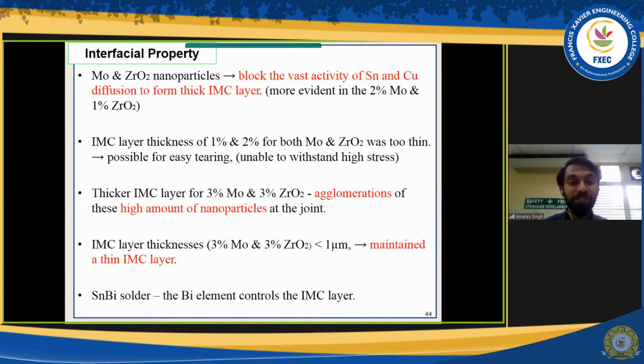So this is a brief summary. You can see that even though 3% of zirconia and 3% of molybdenum measured a larger thickness, it is still less than 1 micrometer. So it maintained a thin IMC layer compared to the other studies.